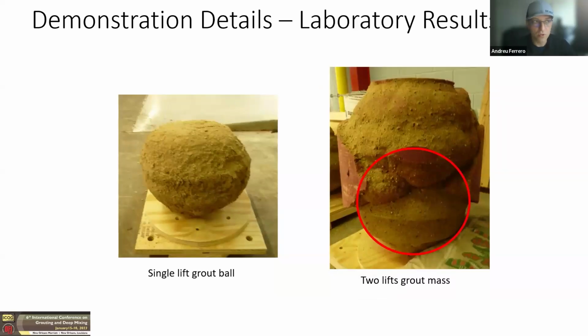These are laboratory results from similar types of open-ended injections. So you can see on the left is a single lift grout ball, and on the right is a double, 2 lifts. So the first grout mass on the bottom stays relatively spherical, and then the second one kind of mushrooms over the top of that one, expanding the diameter a little bit.